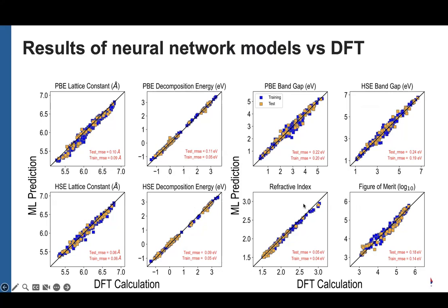But the mitigating factor in hybrid perovskites is that when you involve heavier elements, there's usually a spin orbit coupling interaction. And if you ignore spin orbit, you actually overestimate the band gap. So it's not like a recommended strategy to use error cancellation, but a lot of times it does turn out that way, that errors do cancel, and you get somewhat more reasonable predictions than you would expect otherwise. But we also have HSE band gap, just to give us a sanity check with those.